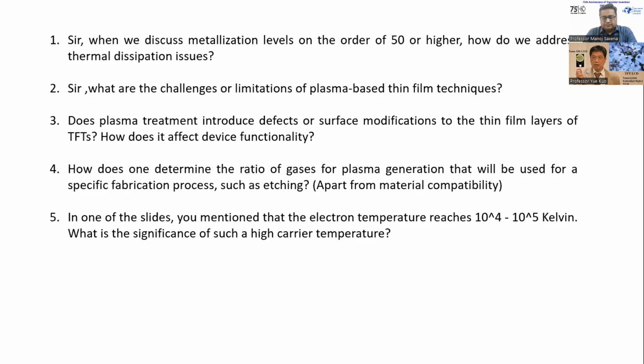You can find it in a literature search. For example, for silicon etching with CF4 plus O2, you want fluorine, which effectively etches silicon. Usually the O2 concentration is, for example, 10%. You can use emission spectroscopy to actually see the fluorine concentration change peaked around that range of concentration. So emission spectroscopy is a very powerful tool for monitoring plasma chemistry. People do use mass spectroscopy, etc., but it's more tedious. With emission spectroscopy, you can get a pretty good idea of the effect of the plasma gas on the plasma chemistry, on the radical formation at least, or some ion formation.